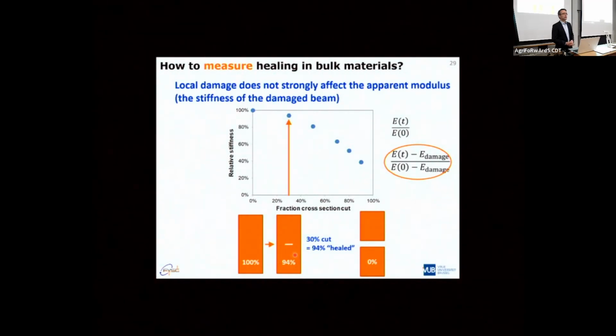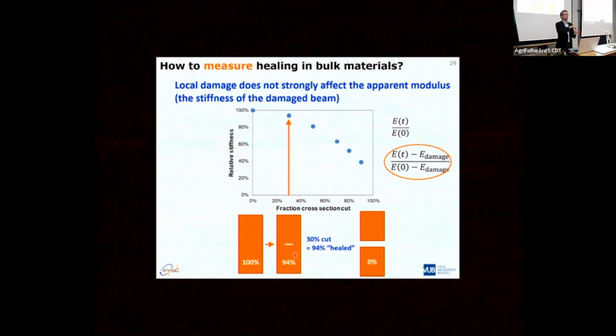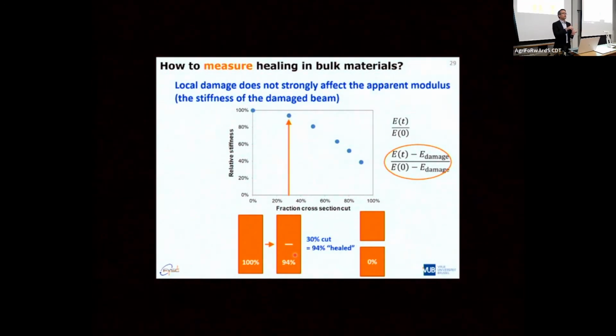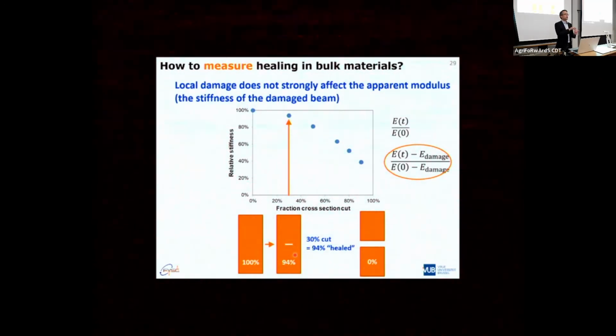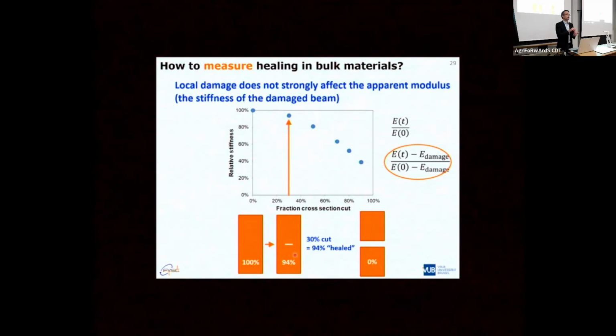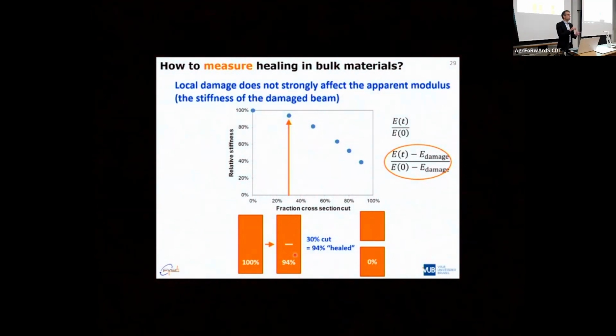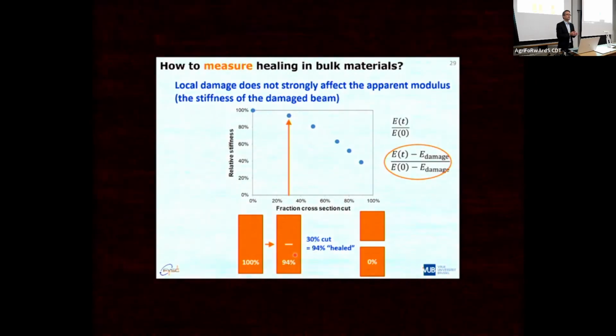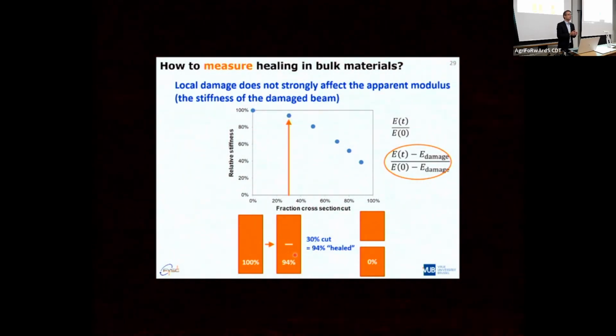So that means that when you put these two together again and you heal and you get 94% of your original modulus, that 30% of your crack plane, your cut plane, is actually probably not even in contact, or at least not bound together. Yeah? So the 94% healing looks very nice, but is not so nice.